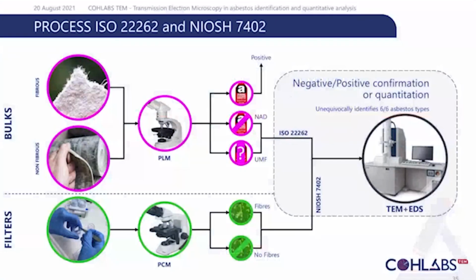Now I'm going to go through the process and standards we're using. In terms of bulks, we are using the process ISO 22262, and for the filters, we're using the NIOSH 7402, which is an American standard. So talking about the bulks, either if it's non-fibrous or fibrous material, we are going to first have these samples analyzed by PLM. That will give us 3 potential outcomes: either it is positive, non-asbestos detected, or unknown mineral fibers. For those last 2 cases, we then prepare the sample using the international standard ISO 22262, and then we proceed to a TEM and EDS analysis to have a negative or a positive confirmation with an unequivocal identification of which asbestos we are looking at.